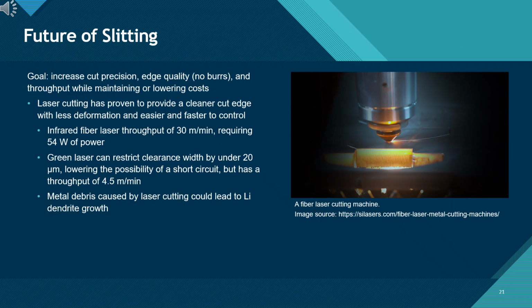Future of slitting. This slide highlights how slitting technology is evolving to improve precision, edge quality, and overall throughput while keeping costs controlled. Laser cutting has become a strong candidate to replace traditional mechanical slitting because it delivers very clean edges with minimal deformation and excellent burr-free quality. Infrared fiber lasers can achieve throughputs of around 30 m/min at low power consumption, about 54 W, making them a fast and efficient option. Green lasers provide even tighter clearance control, below 20 micrometers, which significantly reduces the risk of internal short circuits, though their throughput is slower at around 4.5 m/min.